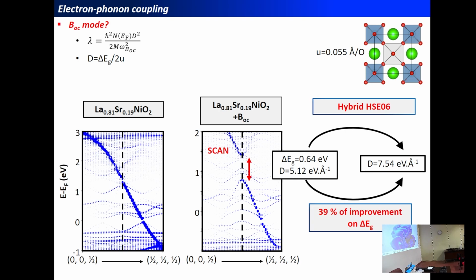So if we do that in the superconducting region of the material, we take the ground-state electronic structure and freeze in some amplitude associated with this vibration, and we see a gap opening estimated at 0.64 eV with the SCAN functional. And so it would yield a reduced electron-phonon coupling of around 5 eV per angstrom. Nevertheless, as I showed you before, the SCAN functional underestimates the band gap properties associated with these nickel oxides. And therefore, for some model systems, we recomputed the gap openings, and we estimated that with hybrid DFT calculations on model systems associated with this nickel oxide, we expect a 40% improvement on this type of gap opening. And therefore, we would expect a reduced electron-phonon coupling matrix element of around 7.5 eV per angstrom.